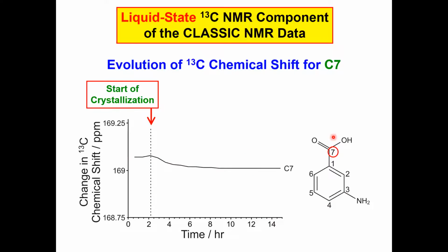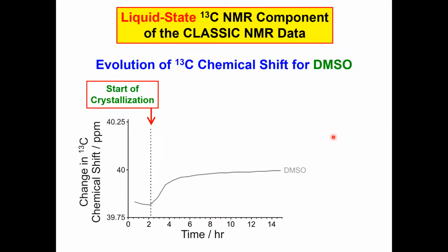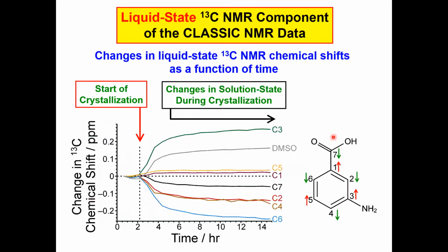And the same arises in its own characteristic way for all the carbon environments in the molecule. And even the solvent, as you can see here, the chemical shift changes in a very well-defined way as a function of time once crystallization is actually proceeding. So how do we interpret all of this information? What I'm doing here is putting all of these data on one graph where I'm expressing the carbon chemical shift relative to the value at time 0. So this is the relative change in carbon chemical shift as a function of time. In the first 2 hours, when nothing is actually happening in the crystallization, there's no change in the chemical shifts. And then as soon as crystals are formed, and as crystal growth proceeds, we see very well-defined changes in all the liquid phase chemical shifts.